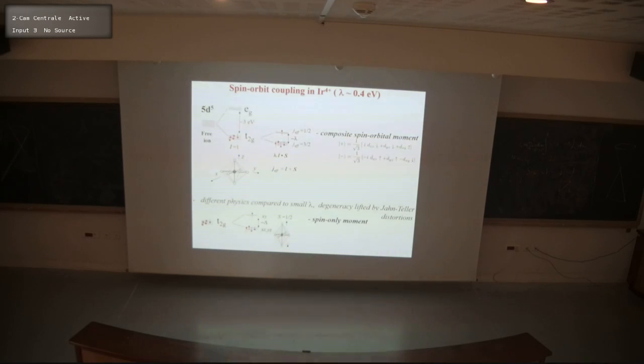However, a very different scenario can happen when we have very strong spin-orbit coupling that overwhelms this energy gain from Jahn-Teller distortions. Iridium is an ion further down the periodic table, where the spin-orbit coupling increases as the atomic number squared as you go down. So it's very large compared to 3d ions. If we think in terms of a one-electron picture, this 3-fold degeneracy is equivalent to an effective orbital angular momentum L equals 1. When the spin-orbit coupling is projected onto this lower manifold, it's written in this form, minus lambda L dot S, where L is the effective orbital angular momentum and S is the spin of the electron.